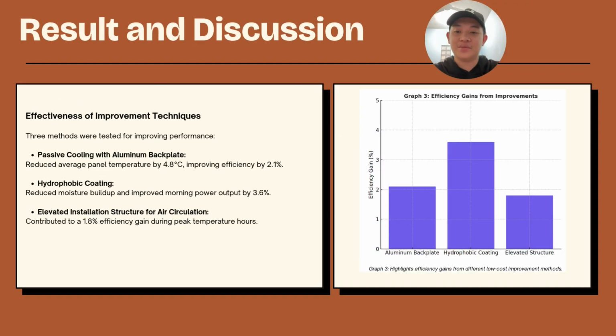Okay, lastly, for the result and discussion, which is effectiveness of improvement techniques, there were 3 methods that were tested for improving performance. First is passive cooling with aluminum backplate, which reduced average panel temperature by 4.8 degrees, improving efficiency by 2.1%. Hydrophobic coating reduced moisture buildup and improved morning power output by 3.6%. Elevated installation structure for air circulation contributed to a 1.8% efficiency gain during peak temperature hours.